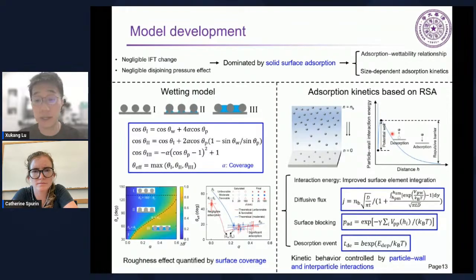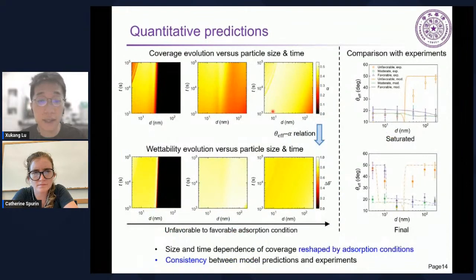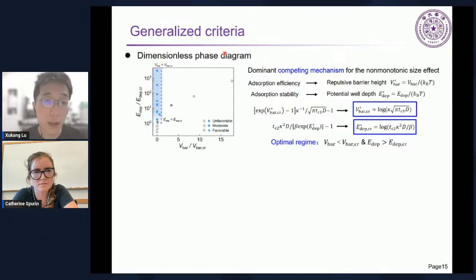So you can see that here is a computation, and this computation is highly size relevant. And then with all this framework, we can do quantitative predictions about everything from coverage evolution to wettability evolution, and we compare our model predictions with experiments, which fit well. But the whole process here is quite complicated. And for practical applications, people may want something simpler and more straightforward to just use and just give the optimal condition. So we further try to develop some generalized criteria theoretically.